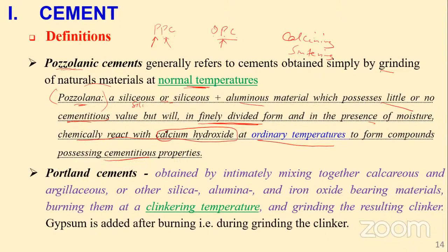So what is the difference between this pozzolanic cement and non-pozzolanic cement? You're saying that when you are producing pozzolans, we do not need to calcine them. You do not need to heat to those sintering temperatures, very high temperatures. But you just need to grind them to a very fine powder, finely divided form. So that when they come into contact with moisture at ordinary temperatures, they can produce those compounds that possess cementitious properties.